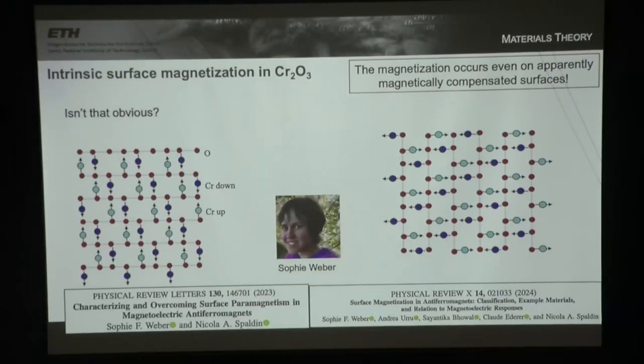magnetization. But what gets really interesting is when one looks at the surfaces, that if you just look at the dipoles, they're magnetically compensated. If I just look at the dipoles here, I'd say there's no net magnetization here. But there is. We know that because there's a component of this magnetoelectric multipole tensor pointing in this direction. And I can see that if I superimpose my hedgehogs on top of the dipoles, it's not magnetically compensated. There's a net surface magnetization. It's only when I naively think of my antiferromagnet as having magnetism coming only from the dipoles that I think it's compensated. It's actually not, in this case, and it's because of the hedgehogs.